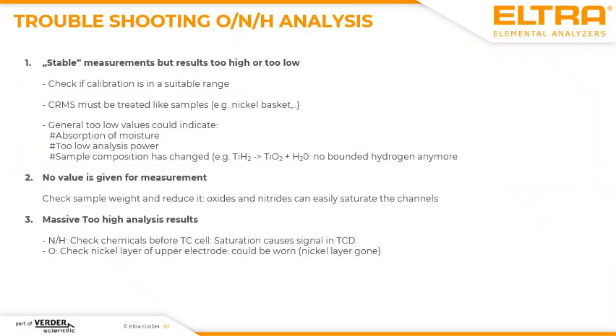When you are facing some trouble with analyzing these powders, usually it's good to follow these rules which are mentioned below. When you get stable results, but the results are too high or too low, check first the calibration, whether your analyzer is calibrated in this calibration range. You can use different reference materials, but please make sure that they always have the same flux